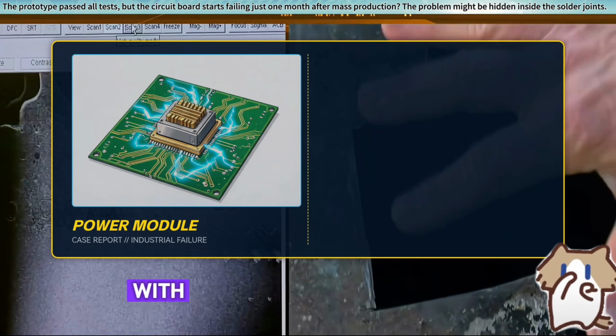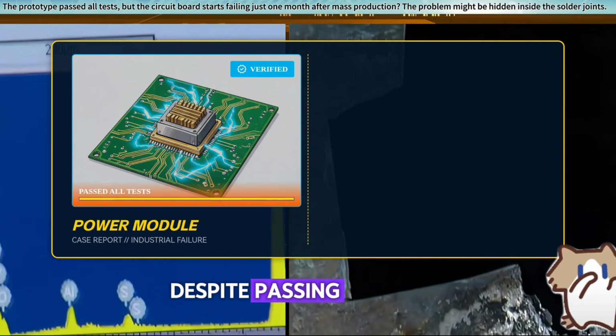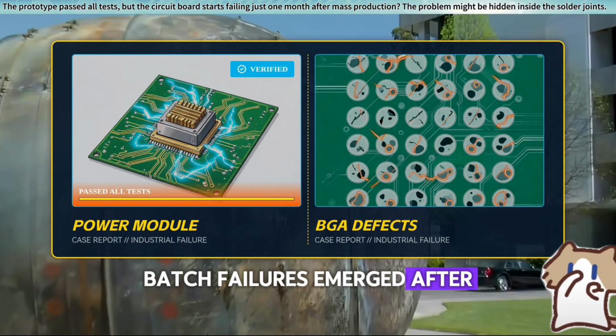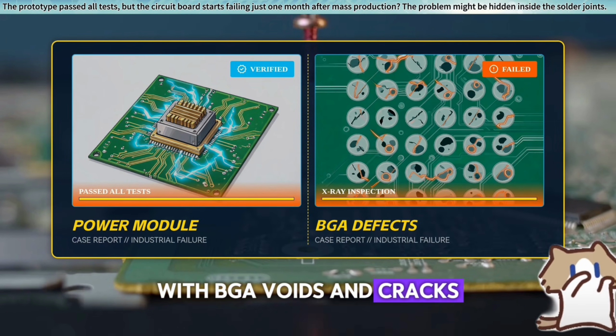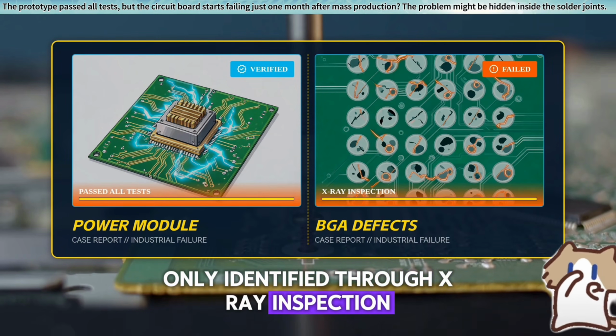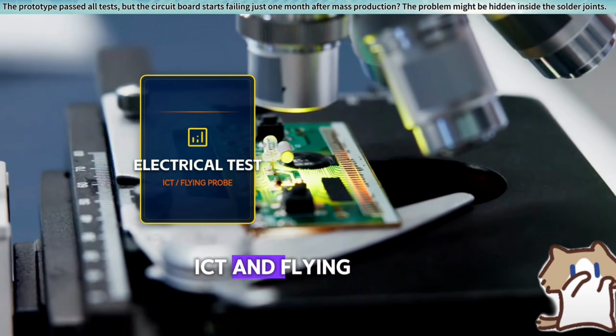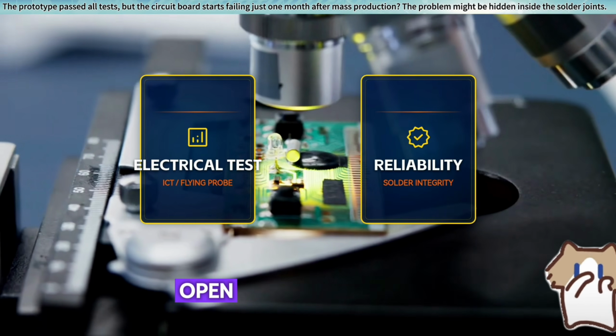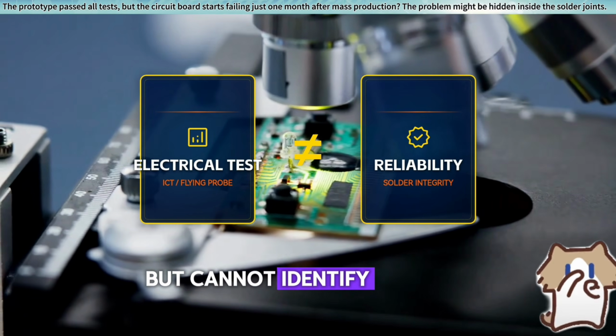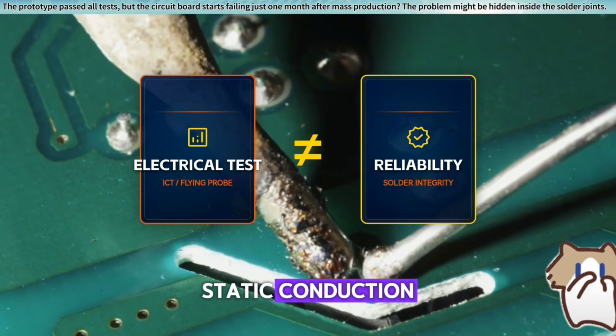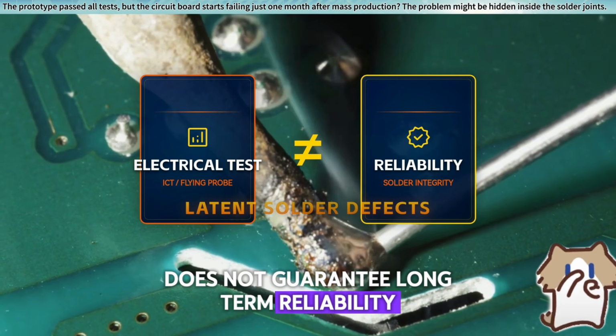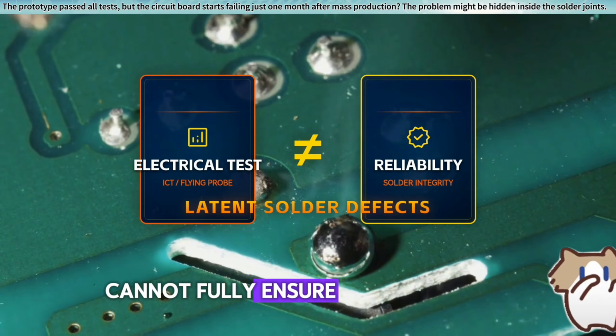Similar cases have occurred with industrial power modules. Despite passing all tests, batch failures emerged after 1 month of use, with BGA voids and cracks only identified through X-ray inspection and metallographic analysis. ICT and flying probe testing methods can only detect open or short circuits, but cannot identify internal micro defects. Static conduction does not guarantee long-term reliability, and electrical tests alone cannot fully ensure solder quality.